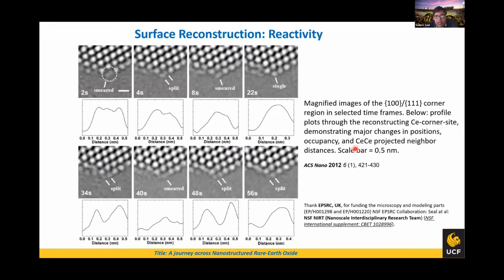This is an interesting work that we did. You can see our papers that I listed here. This is called the surface reconstruction of this material. We created this material, and this is a 111 plane, and this is a 100 plane. We're trying to see under electron radiation really what happens. To summarize this slide, what is happening here is that at the 100 plane, you have the hopping of the cerium atoms going on because the oxygen is much easier to extract from there. So with 2 seconds of radiation, you see a smearing, a split, then a single atom comes in here.